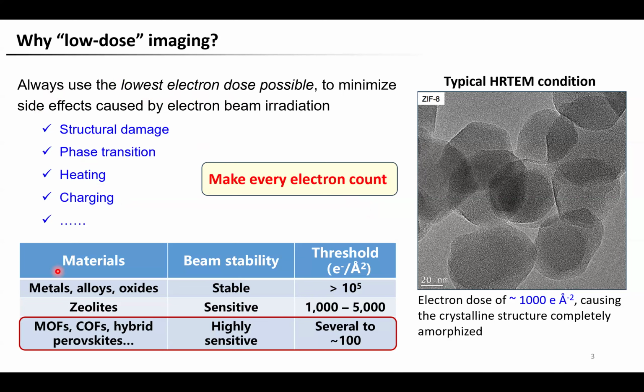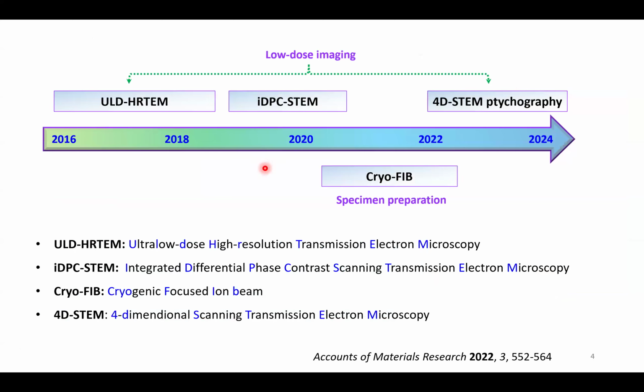So a typical example is metal organic frameworks, MOFs. So here, as you can see, under a very typical TEM condition, the structures of MOF crystals are completely damaged, leaving no structure information recorded in the image. Over the past years, my group has focused on low-dose, high-resolution imaging of sensitive materials under both TEM and STEM modes. And more recently, we started working on 4D STEM-based ptychography. And we are also interested in developing specimen preparation protocols for sensitive materials. Well, in today's presentation, I will focus on the imaging part.